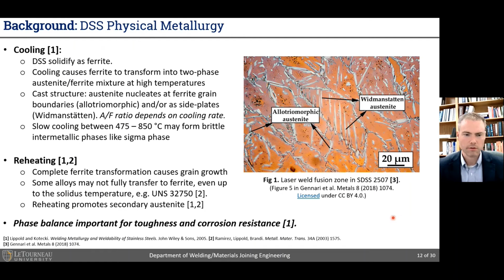So all duplex stainless steels will solidify from the liquid as ferrite, and upon further cooling, this fully ferritic microstructure will enter a two-phase regime in the phase space where austenite will begin to nucleate from ferrite grain boundaries, and in some cases may form these Widmanstätten or side plate morphologies. This is an example of a cast type structure reported by Gennari et al.